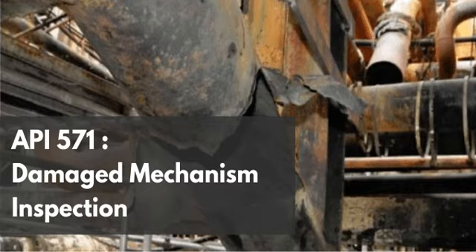Okay. And API 571 draws a very clear line in the sand here, dividing these 400 series alloys into two distinct risk categories based purely on their chromium thresholds. Okay, let's start with the lower risk category then. Which ones are those? The lower chromium alloys listed in the text are 405, 409, 410, and 410S. And what's their chromium percentage? These alloys typically hover around the 11% to 13% chromium mark, maybe just a little bit higher for 409. Okay, 11 to 13%. And the code explicitly states that these specific grades are significantly less susceptible to embrittlement.